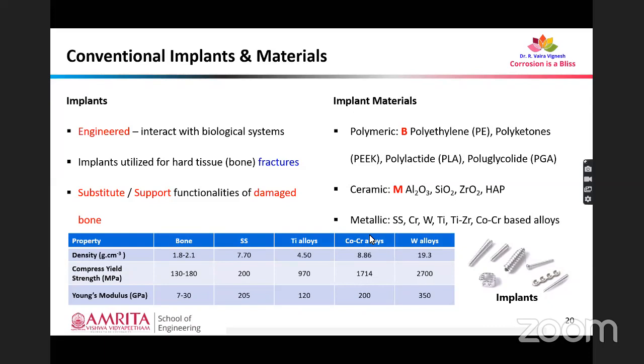Implant materials may be of polymeric, ceramic, or metallic types. The problem with polymeric types is their limited biocompatibility. Coming towards ceramics, we can go with alumina, silica, zirconia, or hydroxyapatite based ceramic materials for implant fabrication, but they have limited machinability characteristics. Coming towards metallic materials, conventionally people use stainless steel, chromium, tungsten, titanium, and cobalt chromium based alloys. But the problem with these conventional metallic systems is that they have very high density, compressive yield strength, and Young's modulus compared to the human bone.